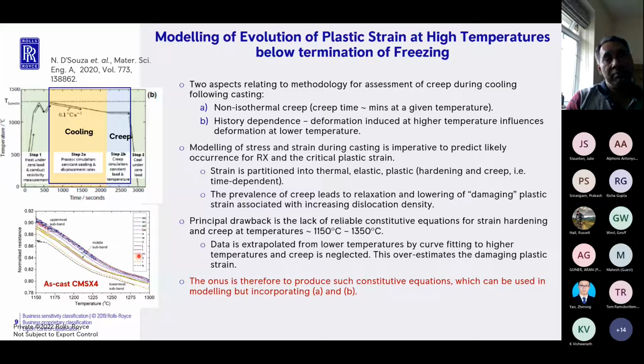But whilst this may seem reasonably straightforward, it is far from straightforward. One of the main reasons is that any model is only as accurate as the data that you supply to it. If you look at typical models that people generally run, at lower temperatures, typically about 1100 or 1000 degrees, there's a lot of reliable data in the literature as well as our own measurements, and models are reasonably accurate. But when you come to high temperatures, typically of the order of about 1300, data is very scarce. And the ones that do exist are, at the very best, less reliable than you might think.